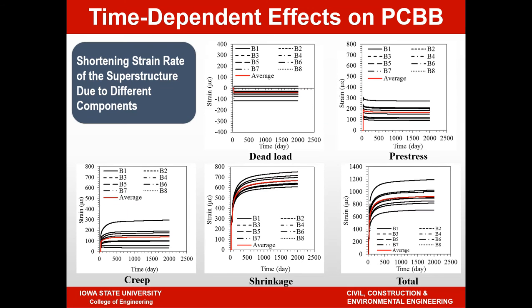What I'm showing here is the different strains that develop in all eight bridges, along with the average you would calculate. And then you also see the total effects shown in the bottom right corner here. Starting from the dead load at the top, you have the dead load strains and the pre-stress strain. Remember the pre-stresses are different, so that's why you're seeing different strains.